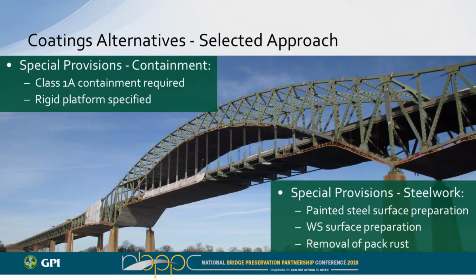And then we also specified rigid platform for that containment. We actually got quite a bit of blowback from the contractors on this initially. The more flexible method of chain link fence with a tarp on top of it is a lot cheaper for them, but there's a lot of problems with it. Those tarps wear out quick. You get a lot of release of the abrasive blast media or the spent materials down into the environment, and we didn't want that again with the lead base. So we specified the rigid platform.